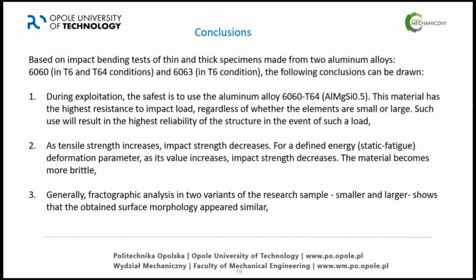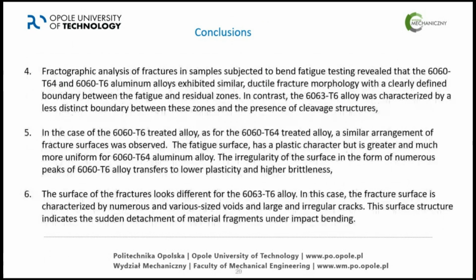Generally, fractographic analysis of two variants of the research sample, smaller and larger, shows that the obtained surface morphology appears similar. You see that the topography was similar. Fractographic analysis of fracture surfaces of samples subjected to bend fatigue testing showed that the 6060 T64 and T6 aluminum alloys exhibit similar ductile fracture morphology, with a clearly defined boundary between the fatigue and residual zones. In contrast, the 6063 T6 alloy was characterized by a less distinct boundary between these zones and the presence of cleavage structure. In the case of the 6060 T6 alloy, a similar arrangement of fracture surfaces was observed.